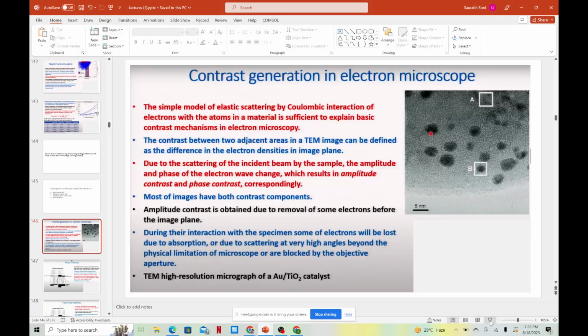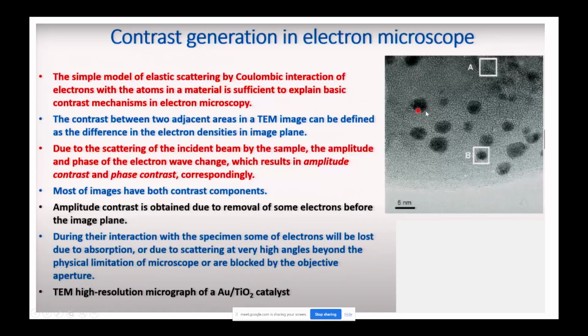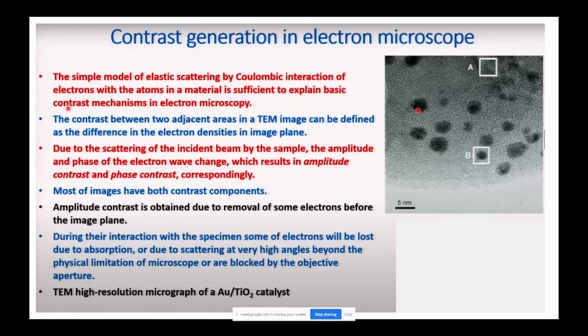So here, as you can see, there is a difference in the contrast from this place to this place. The simple model of elastic scattering by Coulombic interaction of electrons with the atoms in a material is sufficient to explain the basic contrast mechanism in electron microscopy. The contrast between two adjacent areas in TEM images can be defined as the difference in the electron densities in the image plane. Here you can see the contrast difference. Why? Because here the electron density will be different than at this place.